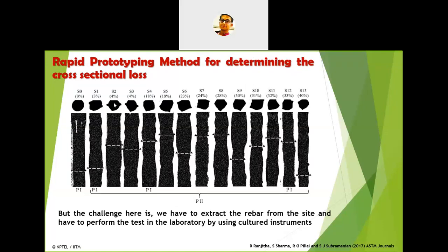So now you can see at the top they have mentioned the cross section, how it looks. So you can see here. Wait, I'm annotating for you. So here you can see that not a single cross section is circular, all are of different shapes. And this particular shape is based on this particular cross section. Like that they have pointed out how the cross section is changing lengthwise. So if you use a vernier caliper to take a diameter, see how wrong it would be.